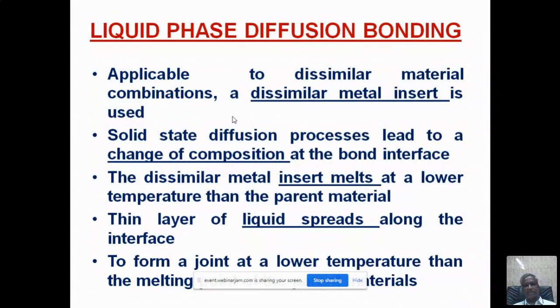So if you heat at 700 degrees centigrade, aluminium will melt. But if you don't heat to that temperature, what will happen? Nothing will happen to the stainless steel. So in that case, they use dissimilar inserts. The inserts are normally silver. Silver will be used. Sometimes copper also will be used. The low melting inserts will be used in between the two different materials.